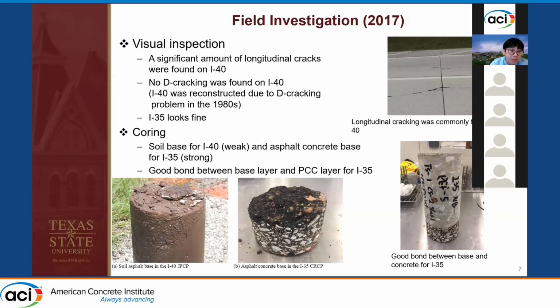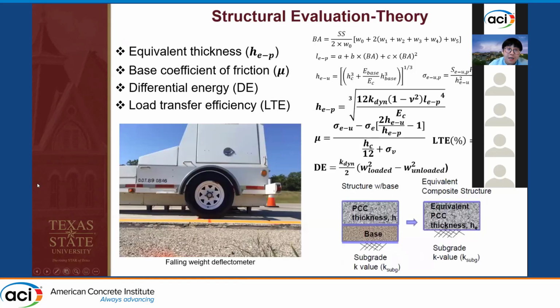And we also were able to core some specimens from the field. And we confirmed that for the I-40, it was asphalt treated soil base. And it appeared that the base was very weak. And for the I-35, we found it was actually asphalt concrete. And we found the asphalt concrete base was very strong. So as you can see in the picture here, we were able to extract a specimen where the base and the slab were not detached, still attached to each other. Then we did FWD, falling weight deflectometer, testing there.